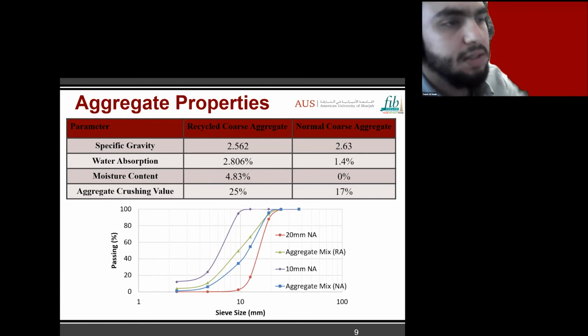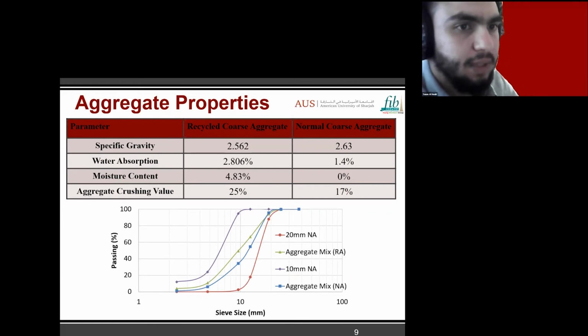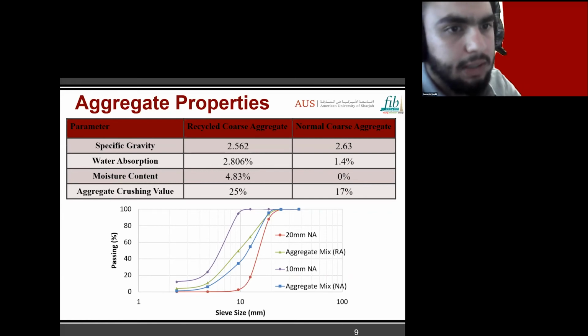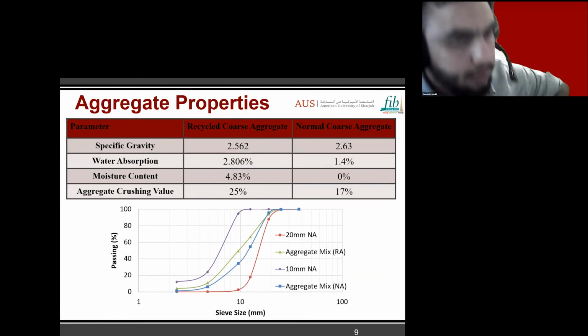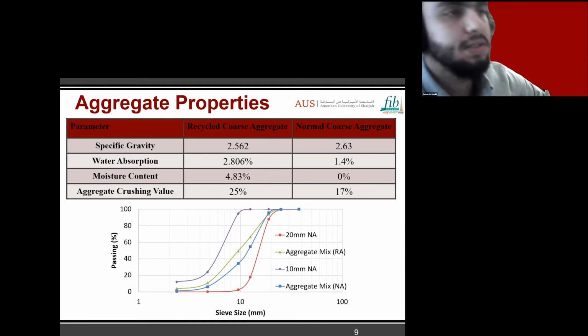The test results show that the RA has much higher absorption ratio and moisture content values than the natural aggregate, owing to the higher porosity of the recycled aggregate as compared to the natural aggregate. However, both recycled aggregate and natural aggregate have aggregate crushing values not exceeding 25%, which classifies them as strong aggregates.